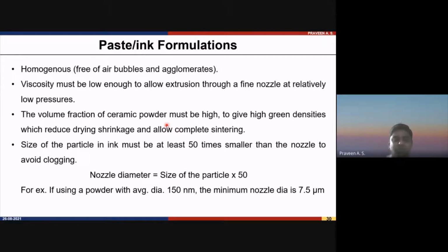So your solid loading, the amount of ceramic particle, should be at least 50 to 80% by volume. If it is beyond 80%, the viscosity of the ink will increase very high. Then your extrusion will become very difficult. From the literature, it is found that 50 to 80% is suitable for realizing the ceramic part without any shrinkage or any part damage.